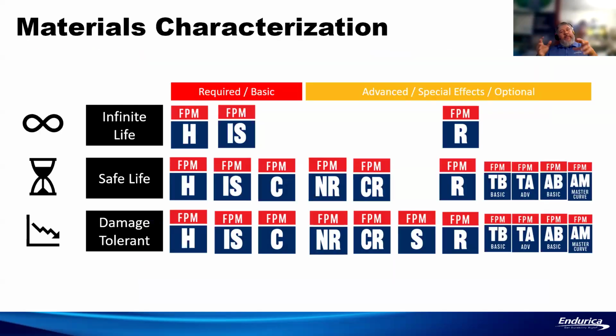Now, if we take these testing modules and map them onto this framework of infinite life versus safe life, this is just a mapping of where you might use any of these modules. If you're using the infinite life approach, you're definitely going to run the hyperelastic and the intrinsic strength, which is the fatigue limit. And then you might also run the reliability module, which is where we measure the distribution of crack precursor sizes in the rubber. That's optional, but you might be interested in the statistical character of that.